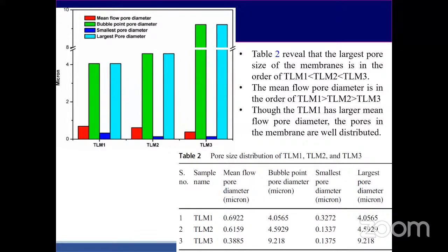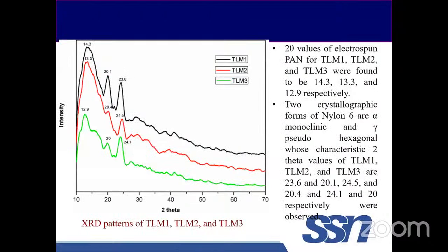clearly seen. Then we checked the XRD of the prepared membranes, where the peaks at 14°, 13° and 12° correspond to the PAN, and 20° and 23° 2 theta correspond to the nylon.